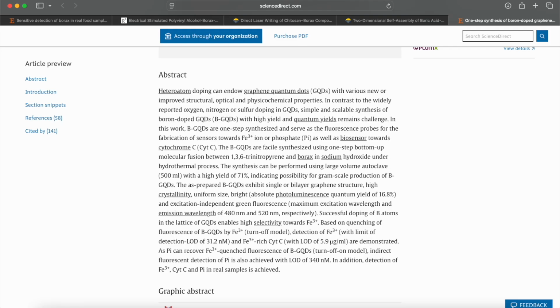The as-prepared boron-doped graphene quantum dots exhibit single or bilayer graphene structure, high crystallinity, uniform size, bright, absolute photoluminescence quantum yield of 16.8%, and excitation-independent green fluorescence. Successful doping of boron atoms in the lattice of graphene quantum dots enables high selectivity towards iron 3. Based on quenching of fluorescence of the boron graphene quantum dots by iron 3, a turn-off model, detection of iron 3 and iron 3 rich cytochrome C are demonstrated.